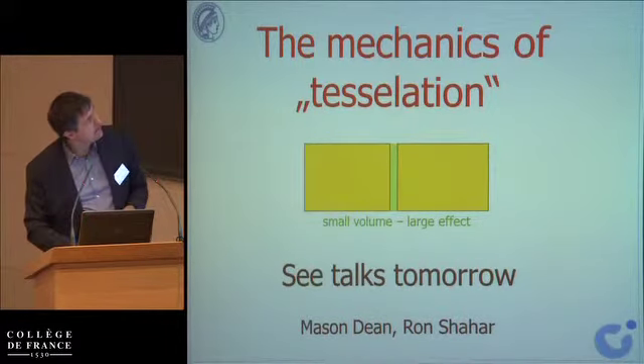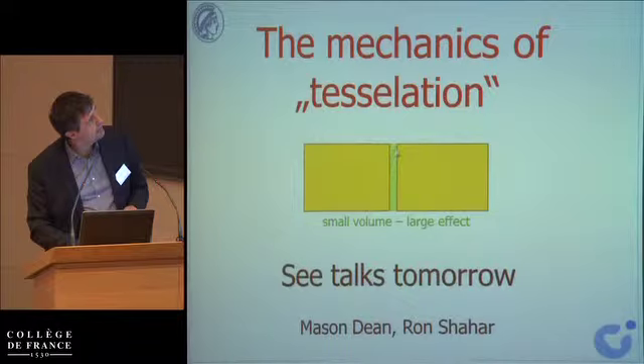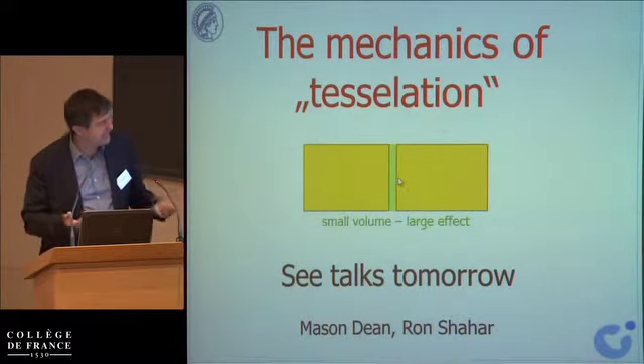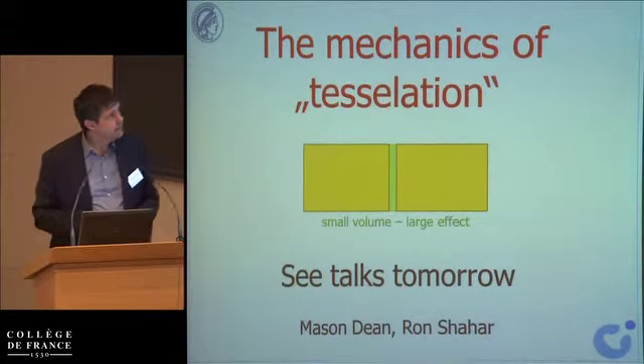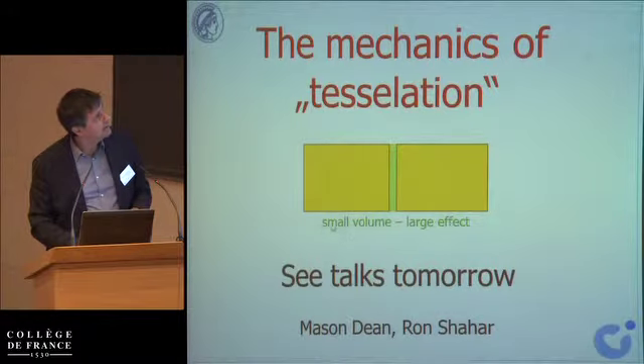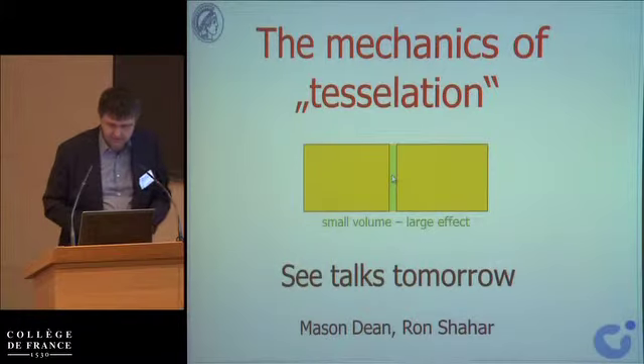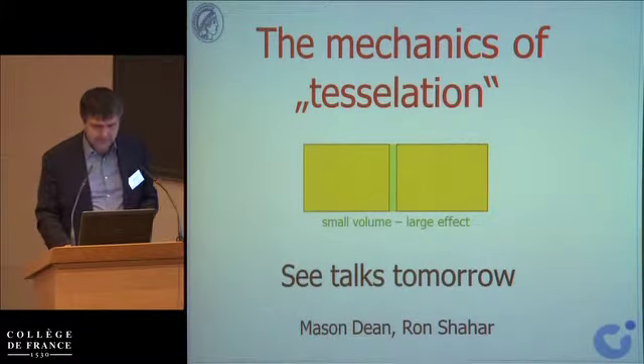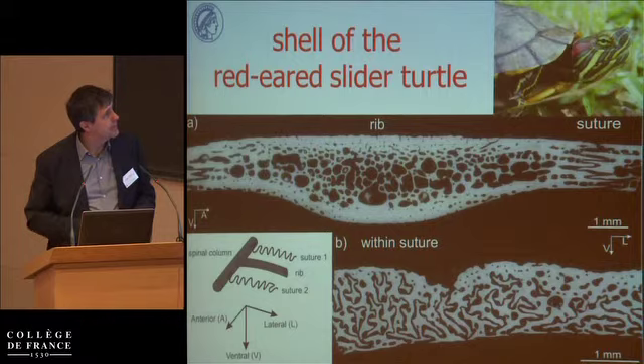Tessellation means take a hard component, another hard component, and a very thin layer, or even nothing, in between. Then clearly this small volume has a very large effect, because in compression it's going to be hard, but if you put tension on this, the soft green phase will actually take the tensile load. So this is a principle that you can see.